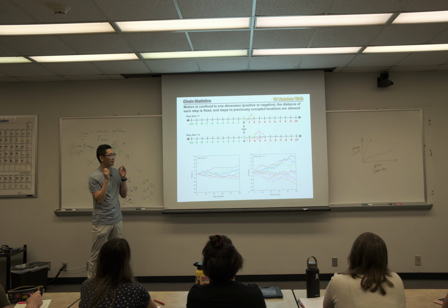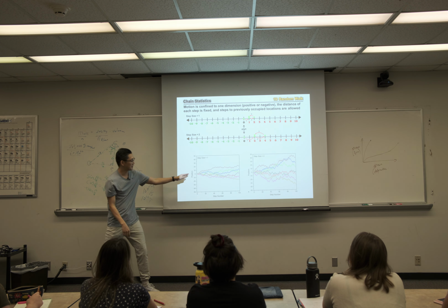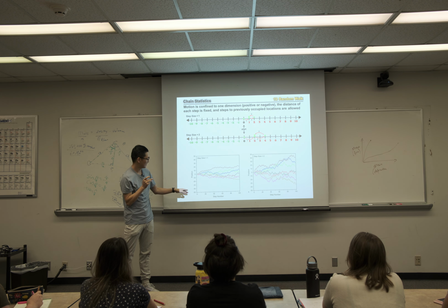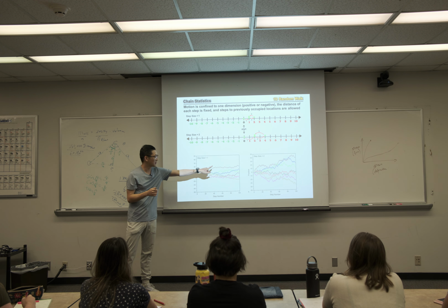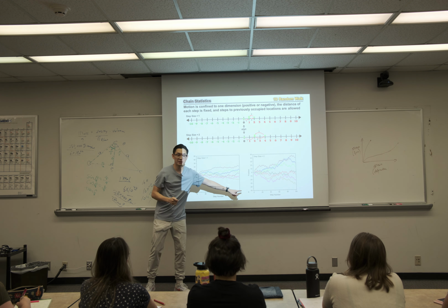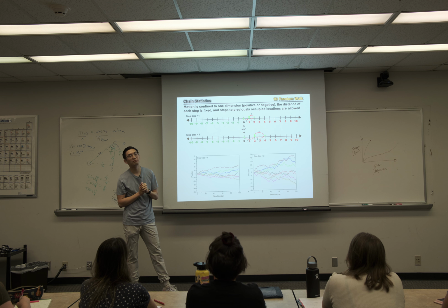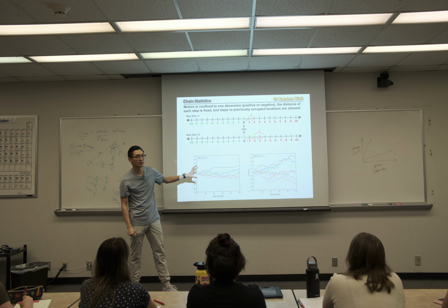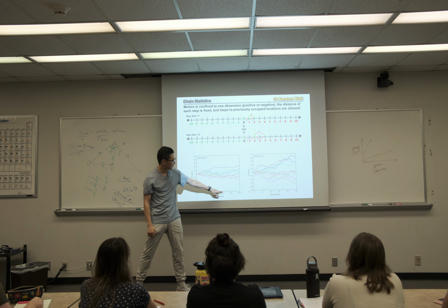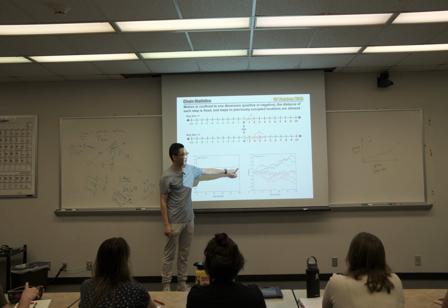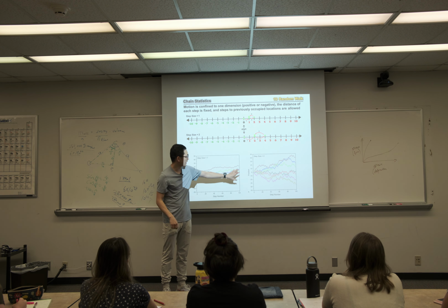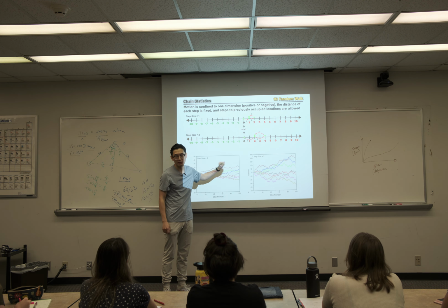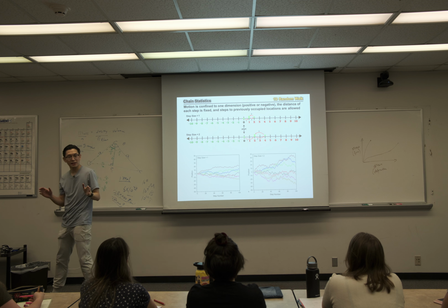So if you now imagine the position is the end-to-end distance, right? Where you start to where you end. The number of steps is the number of bonds. So this is similar. If the number of bonds goes up, it will deviate from where we started. If we take the average, that will be the average end-to-end distance. Does that make sense, everybody?